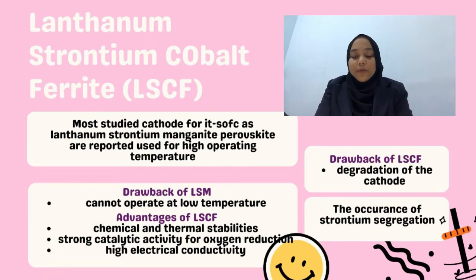However, LSM cannot operate at low temperature due to its high activation energy, which will increase the polarization resistance and decrease the catalytic activity. Hence, new cathode materials of mixed ionic electronic conducting (MIEC) materials are obtained from perovskite-based materials such as LSCF and barium strontium cobaltite ferrite (BSCF). LSCF is a perovskite-based material that is suitable to be used in intermediate temperature SOFC. The reason why LSCF is suitable is because of its good features, such as chemical and thermal stability, strong catalytic activity for oxygen reduction, and high electrical conductivity.